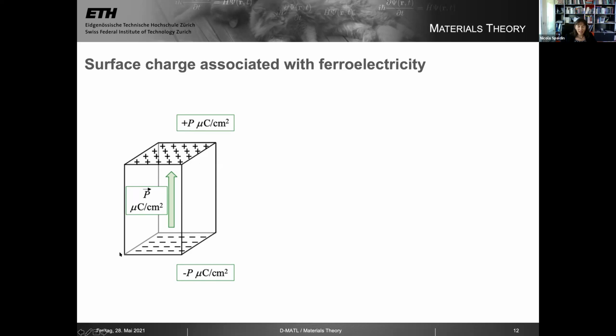And likewise, if I make a surface at the bottom, when the polarization is pointing up, I have a surface charge whose size is equal to the bulk polarization, but whose sign is now minus. I have minus P microcoulombs of charge on the bottom surface for every square centimeter of surface. Okay. And this one can see just from dimensional analysis. So this surface charge is very nice if you're, for example, interested in catalysis or electrochemistry, then you want to have a surface charge because it makes a surface reactive.